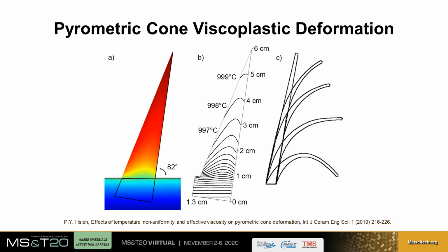Sossman hypothesized that pyrometric cones start to deform at or near the eutectic temperature of the mineral mix used in their fabrication, and that the viscous nature of the molten oxide slows the cone collapse under its own weight. If Sossman is right, then pyrometric cones work by integrating viscoplastic strain over time, where the effective viscosity is controlled by the cone compositions developed by Seger through empirical experimentation.